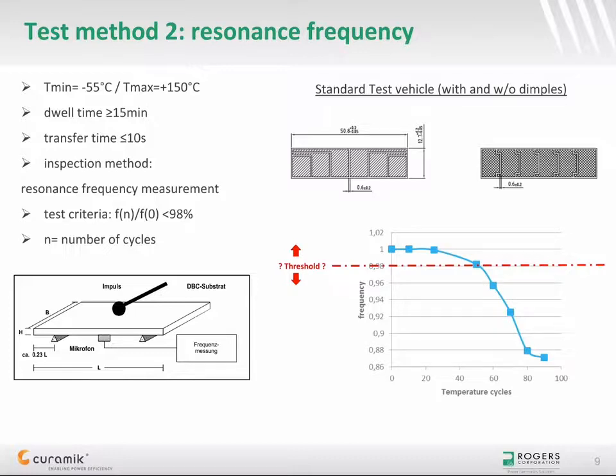Comparison between frequency measurement and dye penetration test has shown that a decrease of frequency by more than 2% correlates with a significant visible degradation of the ceramic. This limit has been set as a threshold for failure for ceramic products in order to compare different kinds of ceramic substrates. However, this doesn't tell anything about the lifetime of a substrate in a power module because the conditions that would apply in a module are completely different. In a module, the substrate is populated with semiconductor devices, attached on a base plate and encapsulated in a plastic housing or molded. As a consequence, copper and ceramic layers no longer have the freedom to expand and shrink with temperature variations as is the case here.